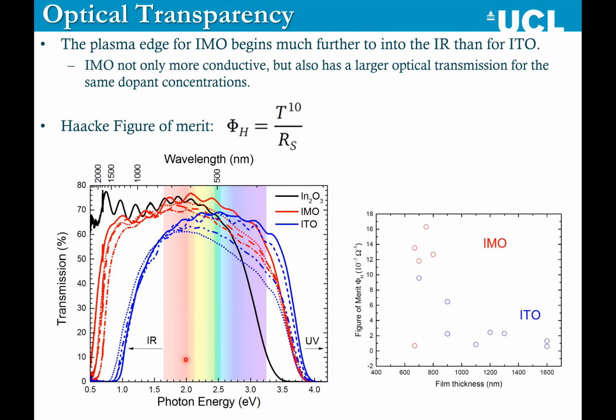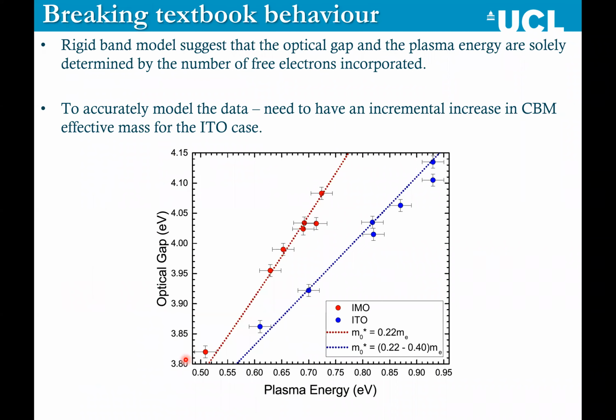So all in, IMO beats ITO hands down. So we went to our colleagues in Liverpool, Professor Tim Veal, and we asked him, could he do some analysis, because he's a very learned colleague when it came to understanding free electron transport in oxides. What he did was fit the optical bandgap versus the plasma energy for these systems. And he could fit the IMO data with a rigid effective mass, or curvature of the conduction band minimum, of 0.22 times the mass of the electron.